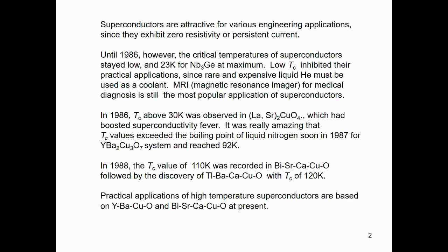In 1986, Tc above 30 K was observed, which boosted the superconductivity fever. And soon after the discovery, the YBCO, that's yttrium barium 2 copper 3 O 7 system, with Tc 92 K, higher than the boiling point of liquid nitrogen, was discovered. And right now, practical applications of oxide superconductors or high temperature superconductors are mainly based on yttrium barium copper oxide or bismuth strontium calcium copper oxide.